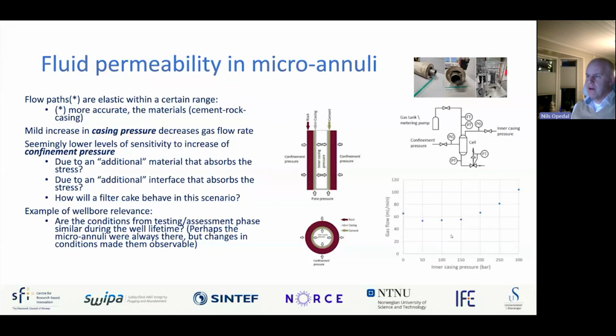For this kind of testing, where we have rock and cement and casing, so three component systems, we have seemingly lower levels of sensitivity from the confinement pressure. So we don't really know why that is yet. This is quite a new set of testing that we're doing. It could be due to an additional material that absorbs stress, or it could be due to an additional interface that absorbs stress. Another thing that we haven't studied yet is how filter cake will behave in this kind of scenario. That means if you have a filter cake at the rock cement interface and you cycle the difference in the confinement pressure while you do a flow test to see how the permeability of your specimen will behave.